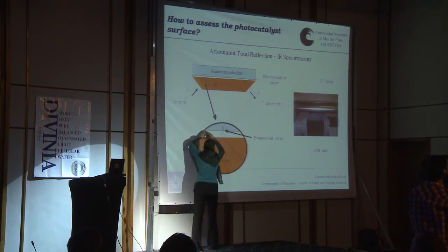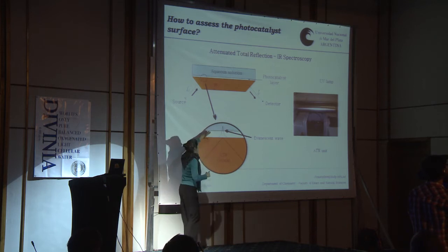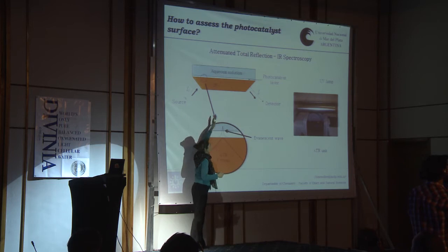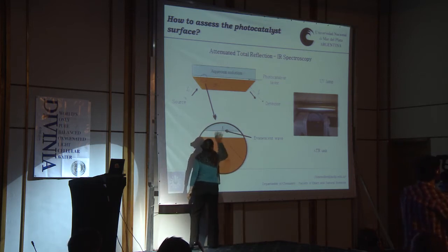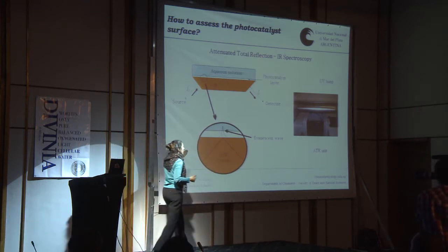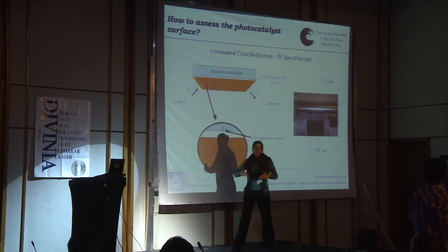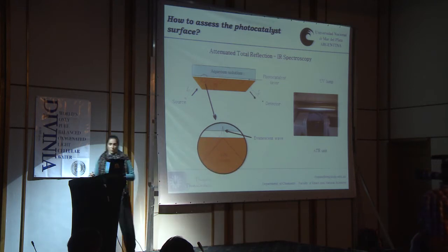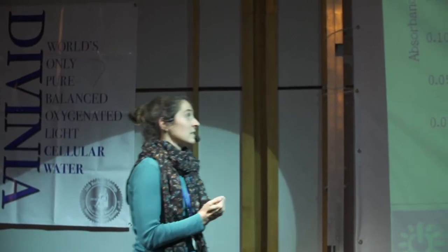So here I prepare a layer of titanium dioxide nanoparticles, a very thin layer between 1.5 to 1.7 micrometers, in contact with the water solution I want to study. In that way, I take information of the adsorbed species, for example. This is what I'm interested in. And I can also put a lamp on top of it and monitor the photocatalytic reactions performing in this moment. So doing all these things, we found very interesting results that we didn't expect.